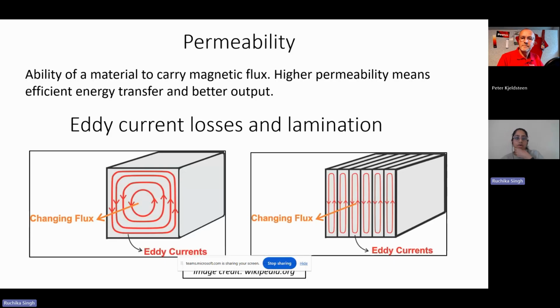And then you also want to minimize core losses. Now, core losses have two components: eddy current losses and hysteresis losses. Eddy current losses are basically due to the eddy currents induced into the material itself by changing magnetic flux, and that is giving rise to eddy current losses. And hysteresis loss itself is when the magnetic domains of the material align and realign when the flux is changing path. You want both of these to be as minimal as possible.